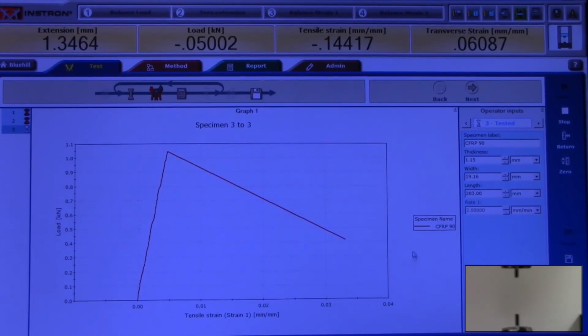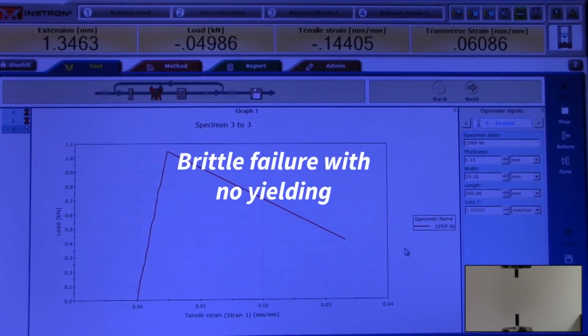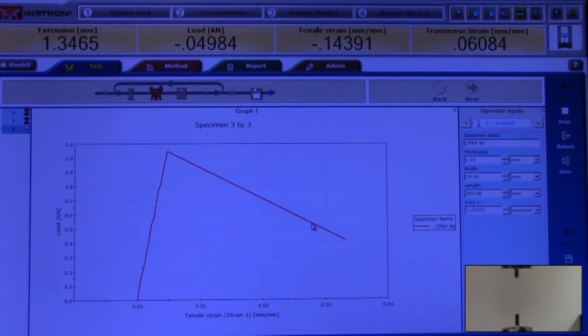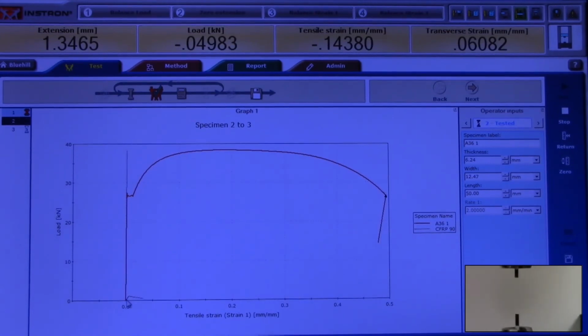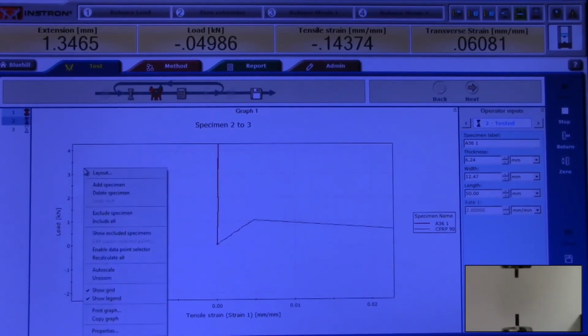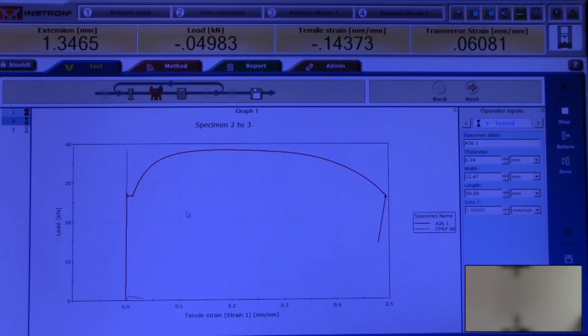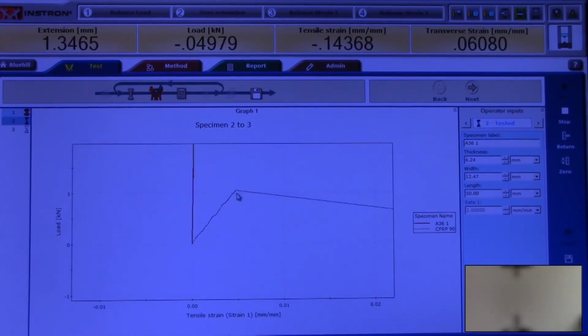All right, so you can see that our specimen just brutally failed. Straight up and snapped off. Compared to the steel, my 90-degree carbon fiber specimen is way down here. So not a lot of strength there and not very stiff. So we'll pull that out now, and I'm pretty sure that the final length will be essentially the same as the initial length, but we'll measure that and verify.